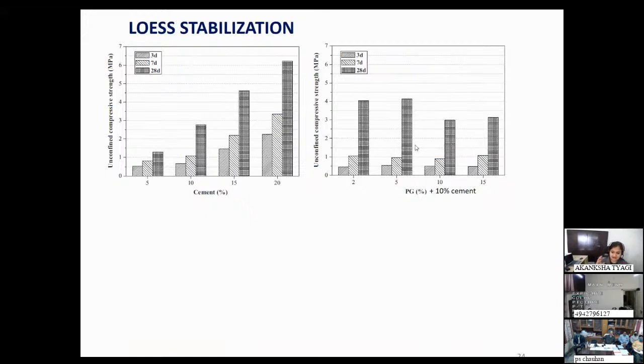Again, when I am discussing the results, you should always keep in mind the background, which type of soil this study is on. It was seen that the addition of phosphogypsum lowered the early strength. The reason was the soluble phosphates, including P2O5, in the unreacted phosphogypsum. It forms a thin film around the cement and lowers the reaction of the cement. Basically, the setting time of the cement is prolonged.